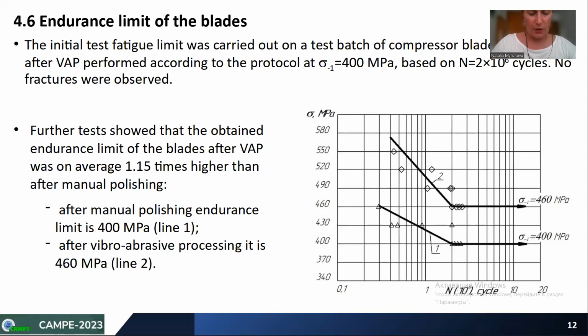The test of fatigue limit showed that the endurance limit of the blades after vibro-abrasive processing was on average 1.15 times higher than after manual polishing. The main reason for the increased fatigue life of the blades as a result of vibro-abrasive polishing is the improvement of the main parameters of the surface layer of the airfoil, which are roughness, surface hardening, and residual stresses. Reducing roughness and eliminating seam marks after milling, technological stress concentrators, and the imposition of compressive residual stresses increase the blade cyclic loading bearing capacity.